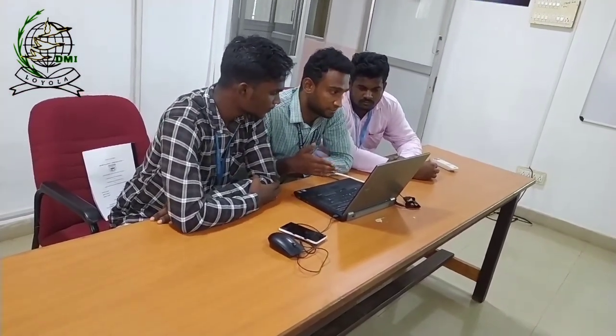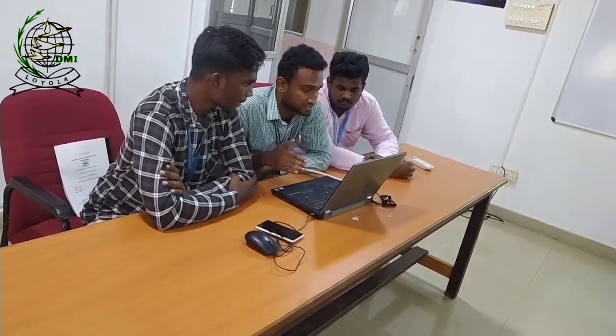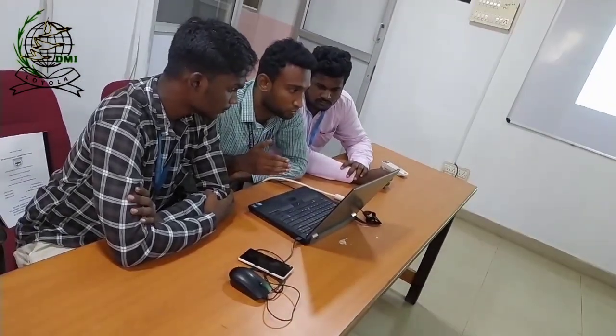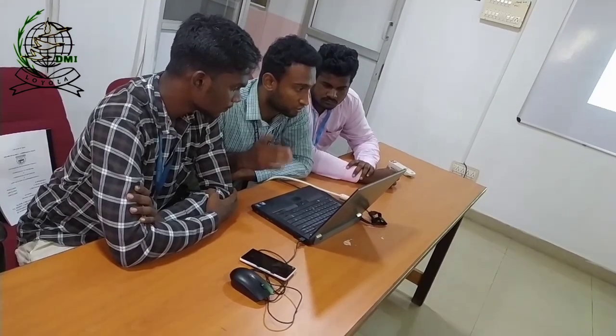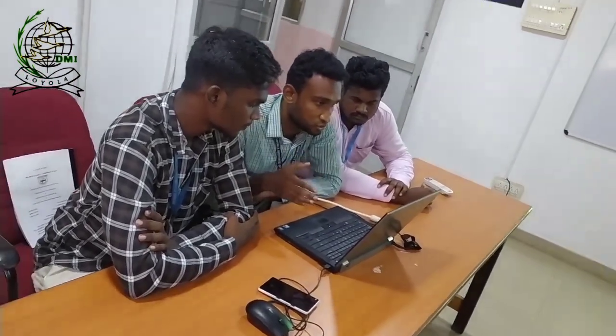Yeah, sir. Actually, we do face the same issues. I myself am the guide for this project. We did two projects, one with B4C and one with SiC. The SiC one we will present in the next paper. For B4C and SiC, with pure magnesium, it was absolutely right. Using stir casting, we could have a lot of defects in the casting, and dispersion was also quite difficult in the earlier stages. So we had to work on sometimes 2 or 3 melts to get the exact one, because when the die is new and the pit furnace is new, we are able to get the exact dispersions. That is why we just use the stir casting method, for proper dissolving of B4C in the material.